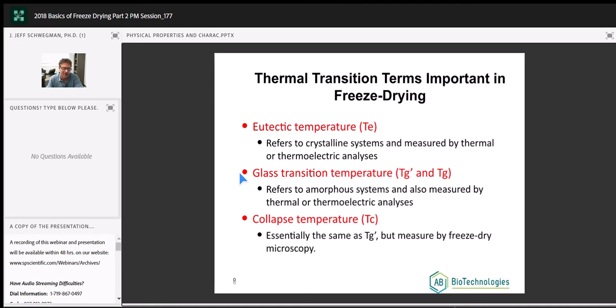Now let's think about this. If we're freeze drying, and we freeze the sample, it's solid, we start removing the ice. Now ice also acts as scaffolding to hold up the physical structure of our frozen solid. Now if we're removing the scaffolding of ice, and say we're above the glass transition temperature or the eutectic melting temperature, the interstitial space is a fluid. So we start pulling the scaffolding out, which is the ice, through primary drying, and if what's left over is a fluid, this is where we're going to get collapse or melt back, not necessarily melt back, but loss of structure of the product. So essentially we dry above these critical temperatures and we're left with a puddle of goo at the bottom of the vial. Okay, we don't want that, obviously.